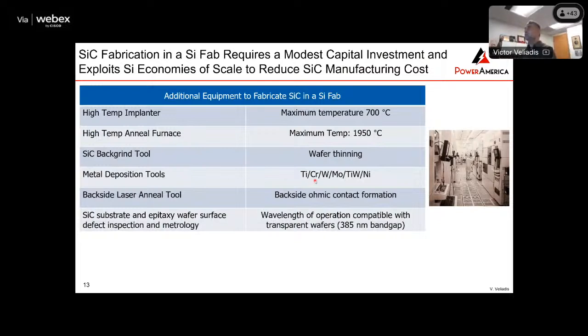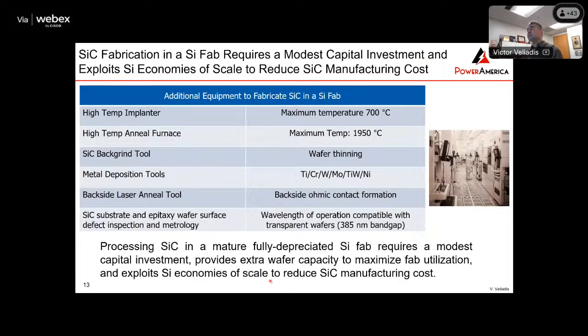When it comes to metals, Ti, chrome, tungsten, molybdenum, these metals here are well matched with respect to CTE, coefficient of thermal expansion, with silicon carbide. Depending on how you do the process, you will likely need a laser anneal tool to create silicide and an ohmic contact in the back of the wafer. And then you need tools that are compatible with the band gap of silicon carbide in order to do optical inspections and metrology.